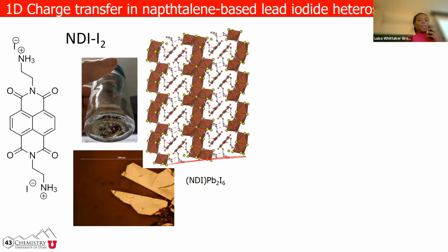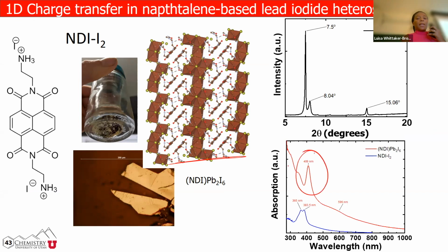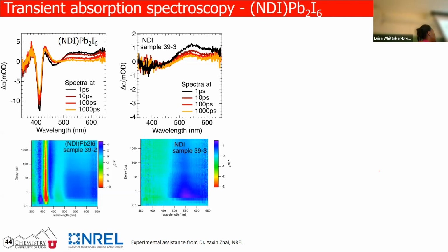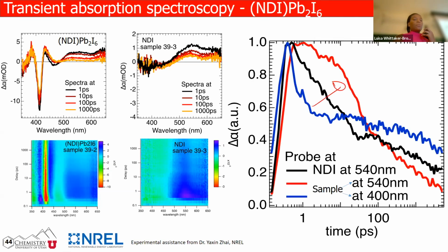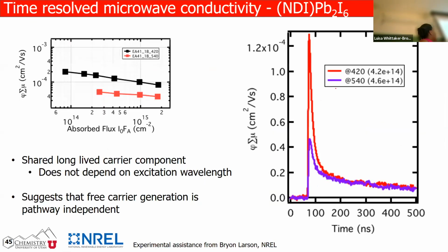Okay, so we were aiming for a two-dimensional system, actually making one-dimensional systems where we make films, and then we see this very strong excitonic peak and this shoulder right here that is basically some charge transfer states. We mapped that again by doing transient absorption experiments, and they have very long-lived carriers, right? Then we complemented that with time-resolved microwave conductivity, where you're actually looking at free carriers, okay? I'm just going to leave it there to see if anybody was paying attention to me at the beginning. With time-resolved microwave conductivity, you are measuring free carriers, okay? You're not measuring excitons, because you're exciting and then looking at free carriers. So with these one-dimensional systems, we have free carriers. And I'm just going to leave it there to see if everybody's going to ask me that question.